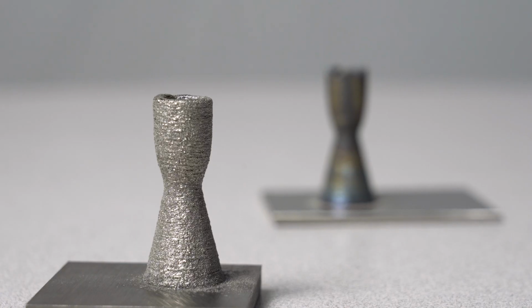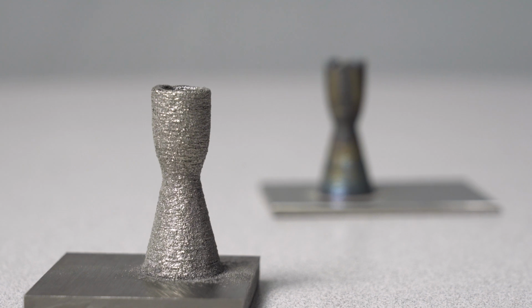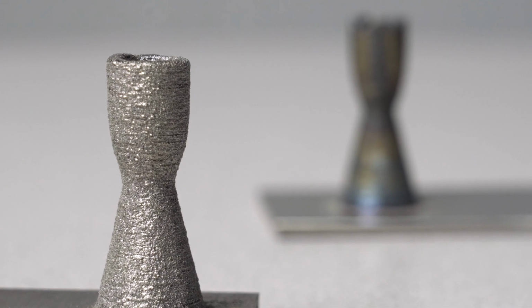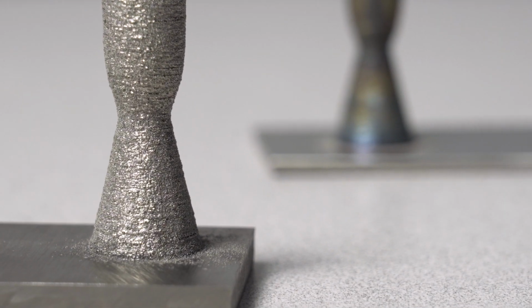You saw that, you got this error, then what change did you make that gave you successful nozzles from that point forward? So to mitigate this going forward, we made sure to have a thicker build plate to again help conduct heat away. We can also raise the temperature a little bit inside the chamber there. You can change the dwell time, essentially start and stop time between layers, to allow heat to conduct away or to cool down a little bit. And so you start managing the thermals in the process, just like you manage the powder feed and the geometry there. And of course, that's where a lot of research now is, in these sort of closed loop systems. Hey, let's sense the temperature, let's sense the height, let's sense the powder flow rate to then make sure that we're building the right part over and over and over again each layer.